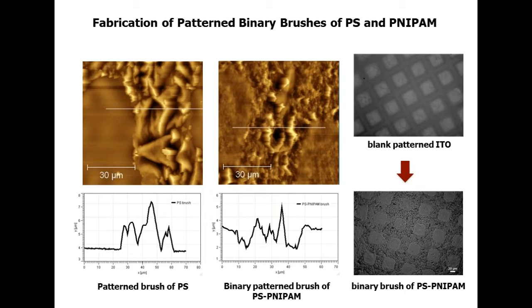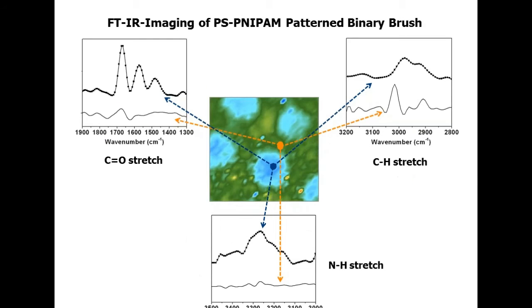So to turn to more combination methods of chemical mapping and spectroscopy and microscopy, we can utilize chemical imaging. In this case, this is a chemical image map of the two polymers based on FTIR imaging with a focal plane array detector. So what we have here is essentially the green color representing that of your polystyrene, and the blue region here representing that of PNIPAM, as observed by the carbonyl, CH, and NH stretching. So quite a powerful tool for differentiating patterns or domains with two different chemistries.